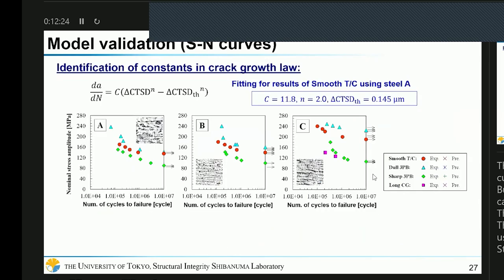And this slide shows our experimental results of the SN curve. So steel A, B, and C, and each graph has various fatigue test data from different specimen shapes. So we can see a sufficiently wide variation of the results. But there is a set of parameters we cannot determine beforehand, and that is the constants in crack growth law. So we identify these 3 parameters using the results of the smooth tension-compression test with steel A. This is the red plot, like this. So we can see very good agreement with experimental results, but note that this is just fitting, not prediction. Now we identified all the parameters, so there are no adjustable fitting parameters anymore.